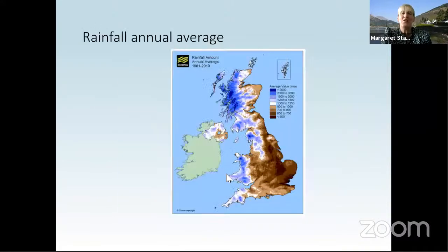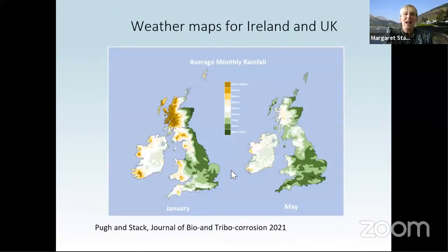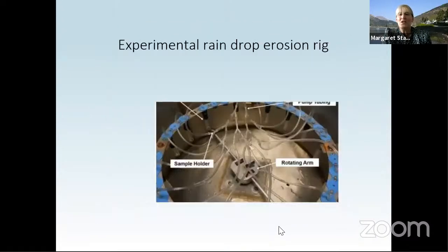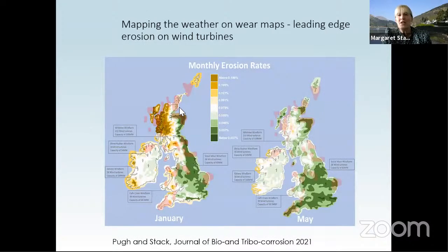So if we just look at our two maps again, rain and hail, and we look at the average monthly rainfall for January and May, we see a big difference, obviously. It's work that we produced earlier this year, looking at testing of a wind turbine. We can generate these maps for January and May for the erosion of the materials, and this is for raindrop erosion of wind turbines. So we can generate erosion maps for the materials, and we've included hail here. The most important thing is that in the different microclimates, you get much higher erosion on the materials.